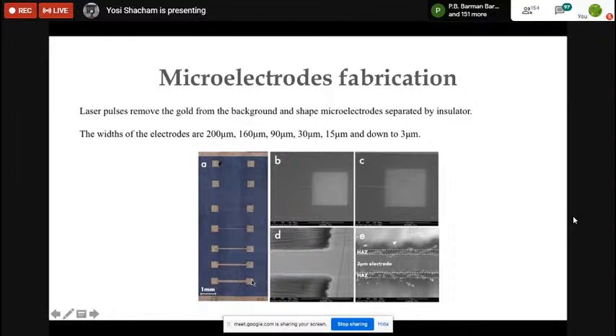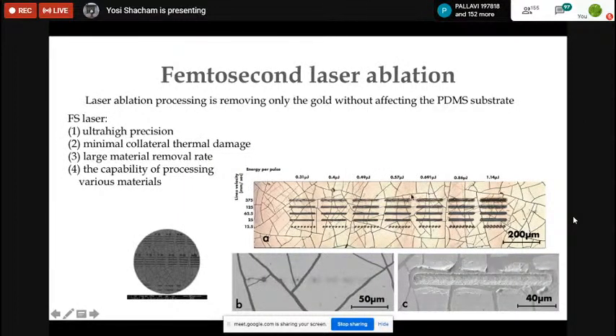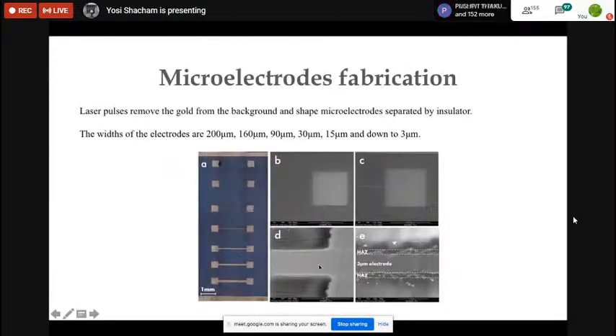This is a better sample. I showed you good samples and also bad samples. The first run had a lot of cracks. The second run was actually much better. And this is the laser processing. We can go down to 3 micron lines, and you can see this is a 3 micron electrode.